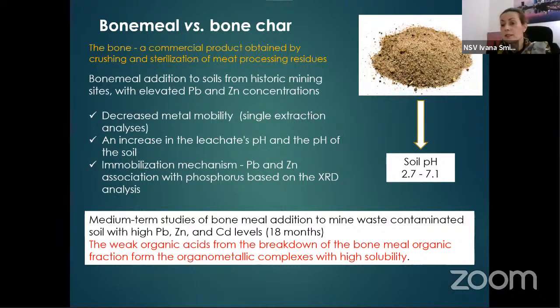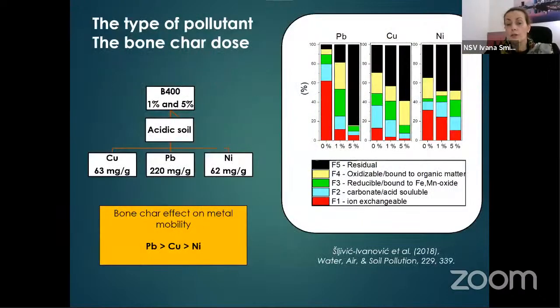However, medium-term and long-term studies have indicated that this organic fraction of bone meal can undergo breakdown in the soil, and the weak organic acids that are formed during this process can form organometallic complexes and even increase the mobility of heavy metals in the soil. So if we have to choose between bone meal and bone char, bone char is a much better choice for metal stabilization. Also, the type of pollutants affects the immobilization efficiency and the dose of the bone char in the soil. This is an example of an experiment conducted in our group.